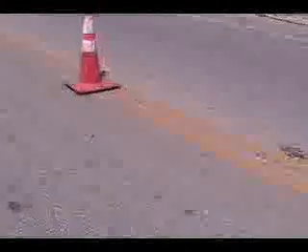This road definitely has weathering occurring, or raveling. If you look at the consistency of the material and then look up at the edge stripe or the center stripe where there's no traffic on either side, there's an area where the roadway is smooth, and then you look back down and all of this is very weathered. So we're going to call this almost 100% ravel, minus the 0.5 meters wide at the center stripe that is not raveled.